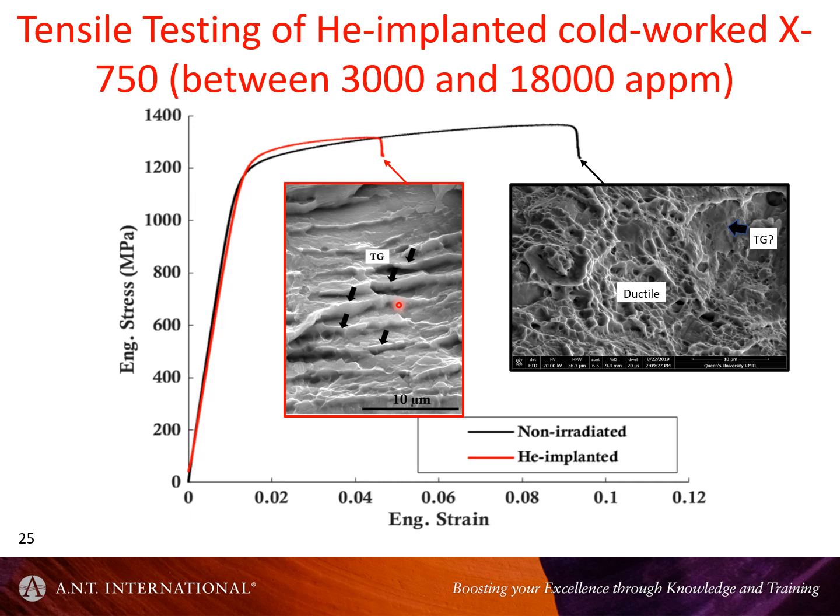I should point out, these were present from fabrication. They weren't induced by either testing or by irradiation. They're present from fabrication. And if you have some which are intersecting the fracture surface, you get these little steps, like not steps, but walls being created. So basically, clearly, you've got preferential fracture along the edge of these features.